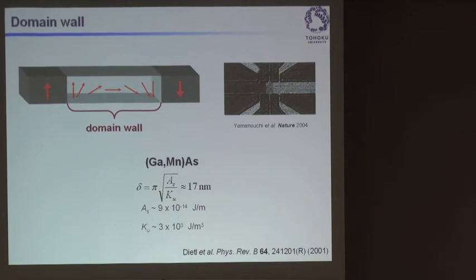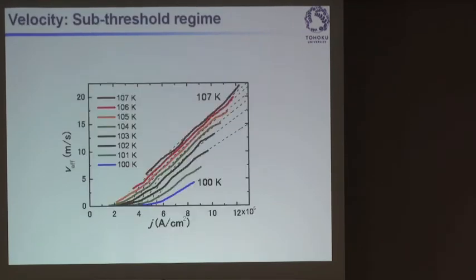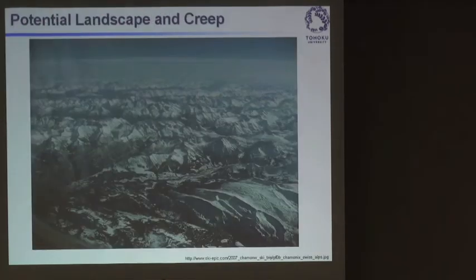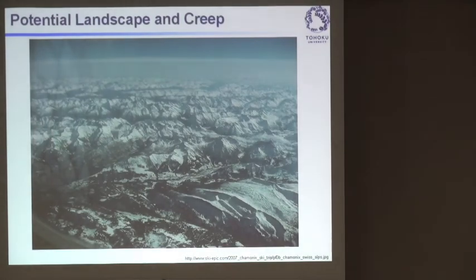I will not go into the details of this domain wall motion, but the result is shown here. This is a current, a spin polarized current, passing through the domain wall. And this is the velocity of the domain wall at various temperatures. This part can be explained by spin transfer torque, and that has also been observed in metallic structures. But the part that has not been fully observed in metallic structures is shown here. If you expand it, we see creep motion.